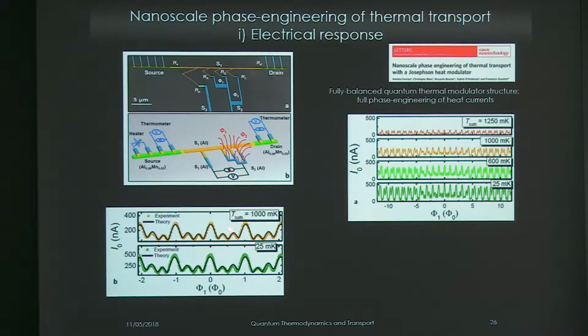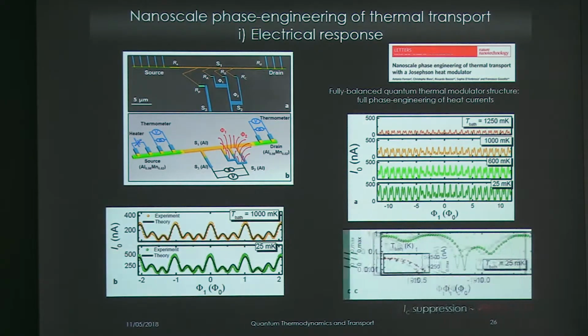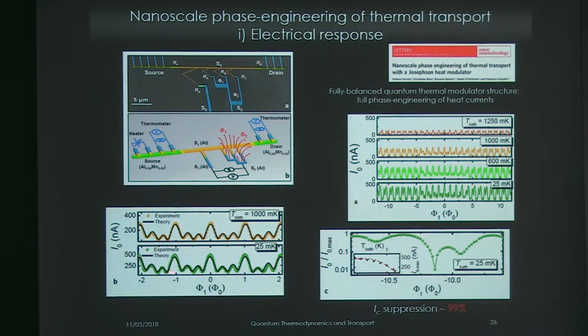But at least from the electrical point of view, these can be easily fitted with RCSJ models, a resistively and capacitively shunted junction model for the junction. So you see that the black line is the fit to the data. So in some sense, one can take very precisely into account the difference of the interferometer. What is important is that from the electrical point of view, it was possible to annihilate the critical current down to 99%, and there was a huge asymmetry between the two junctions. Okay, but this is well known. From the electric point of view, we wanted to demonstrate that it was possible to do the same in the thermal case.